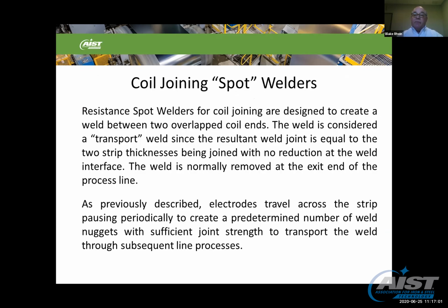The resistance spot welders for coil joining are designed to create a weld between two overlapping coil ends. The weld is considered a transport weld, since the resultant weld joint is equal to the two strip thicknesses being joined, with no reduction at the weld interface. In this case, the weld is normally removed at the exit end of the process line.